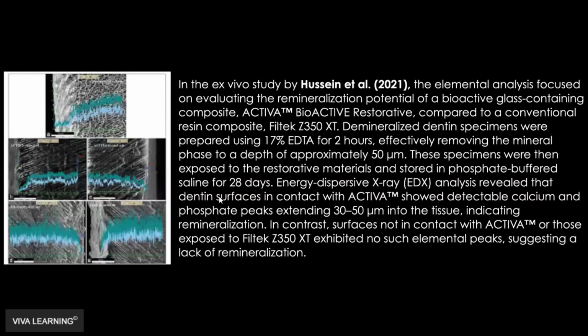And then there's one more here. On this one, what they did is they took the Activa Bioactive restorative material and a traditional composite, and they put them on top of demineralized dentin specimens that they demineralized using, it says here, EDTA, which they said removed the mineral phase up to 50 microns. So these specimens had the restorative material put on top of them. They were put in saline solution. The same EDX was used to look at the amount of calcium and phosphate on the underlying dentin. And essentially the surfaces that were exposed to Activa saw an increase in the amount of calcium and phosphate, whereas the ones that were not exposed to Activa, or those exposed to just regular composite, didn't show any signs of remineralization.